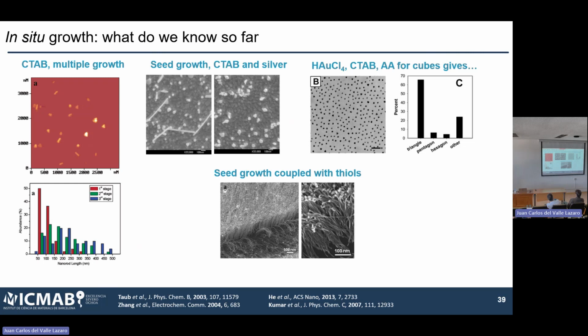And this is a study that I liked a lot, because here you see they presented this paper as a forest of nanowires. This is a clear example of what gets me most excited about in situ growth, which is that there are structures that you can grow in situ that you will never be able to grow in solution. If I grow nanowires in solution, no matter what you do, you will never get this, ever. So there is a space where in situ growth can bring new players to the table, can give us new systems to play with.